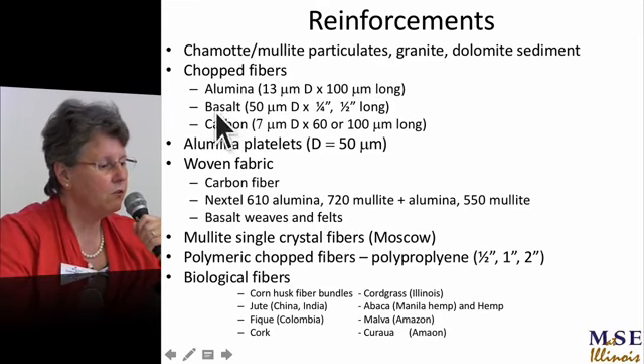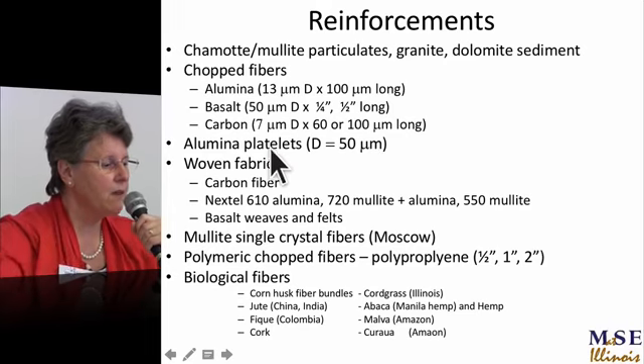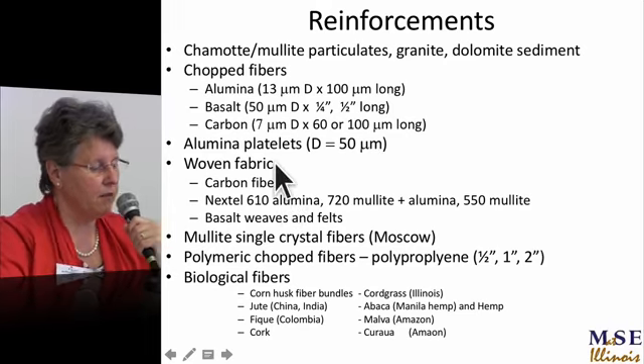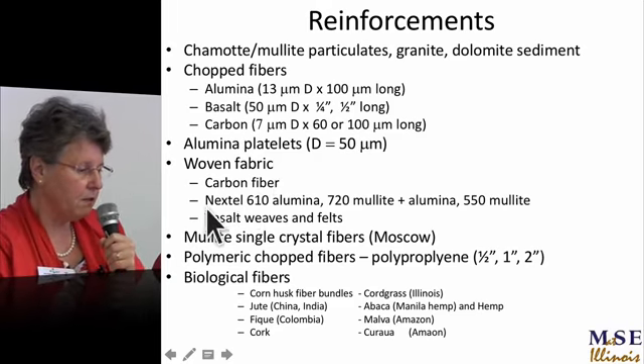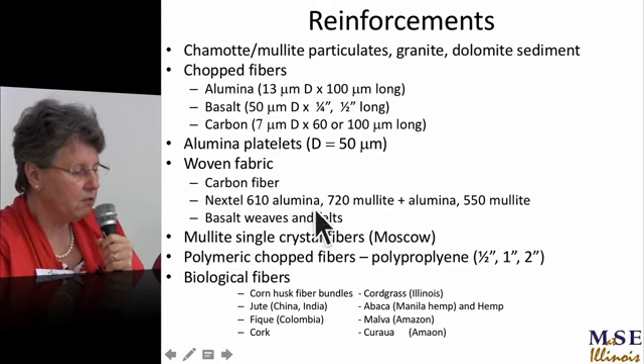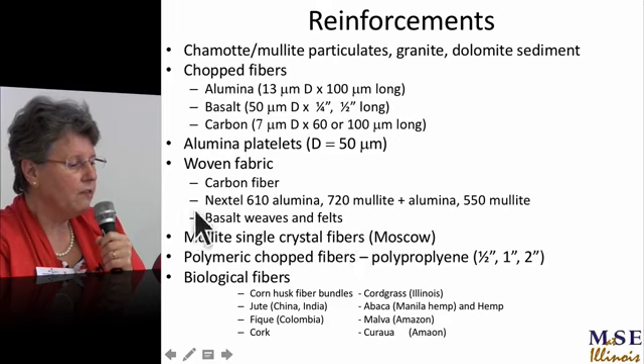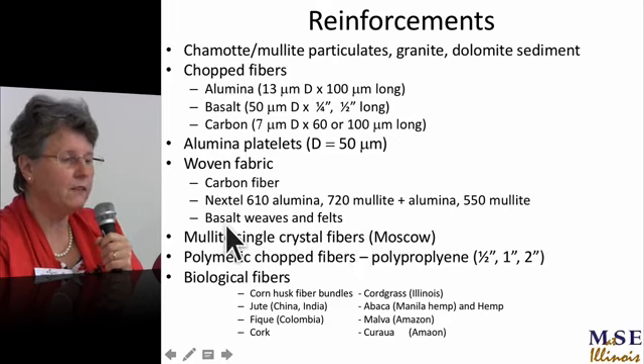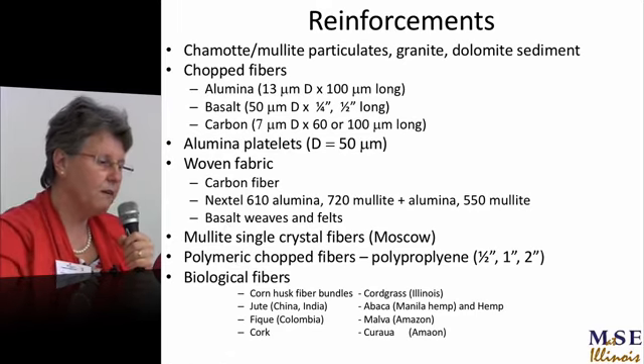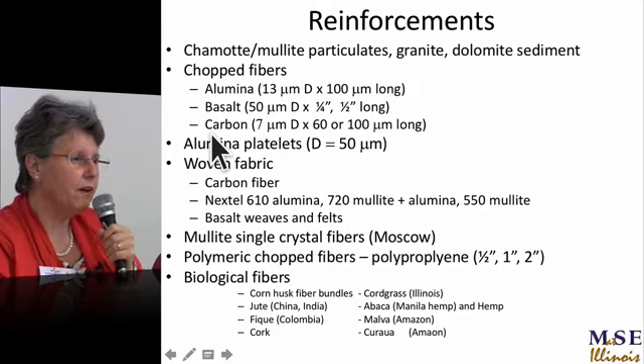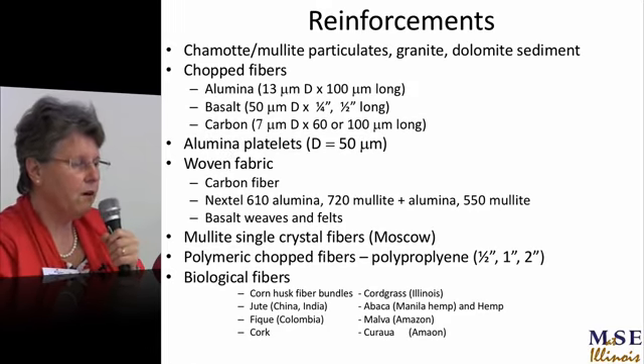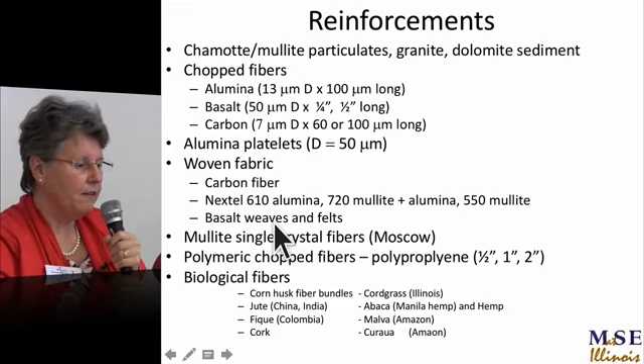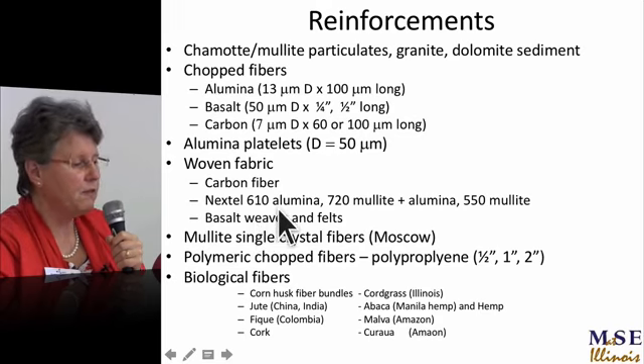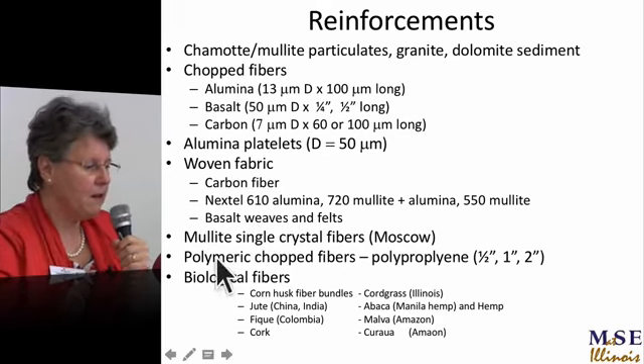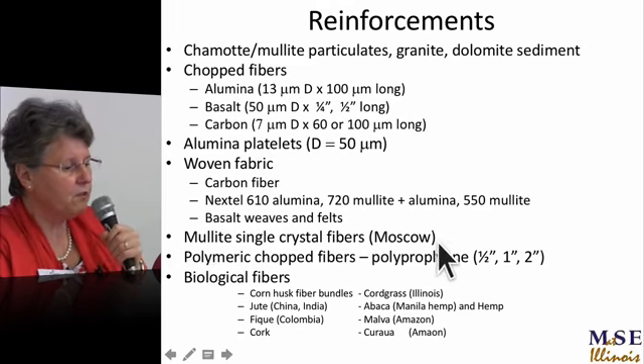Chopped fibres, alumina fibres, basalt fibres, carbon fibres, alumina platelets from grinding media, fabrics, you know, and there's long fibres, and then fabrics, carbon fibre, and then Nextel 610, alumina 720. Basalt weaves. The basalt fibres from Technobasalt in Kiev, and also Kamenny Vek, Moscow. They produce good basalt fibres, 1200 C capability, and these can be used as a cheap but pretty good reinforcement compared with the expensive 3M Nextel fibres. I've got some mullite single crystal fibres from Moscow with love.